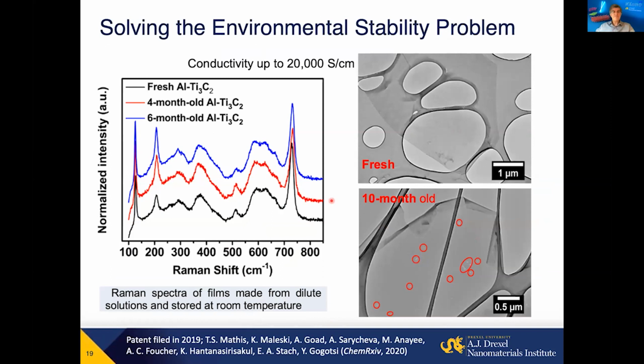And while in assembled film, they have stability for at least several years. We have films which were made years ago, and they still keep their properties to a large extent. Single layer flakes could not stay in water for more than a week or two, or deep refrigeration was required, or transfer to non-aqueous environment.